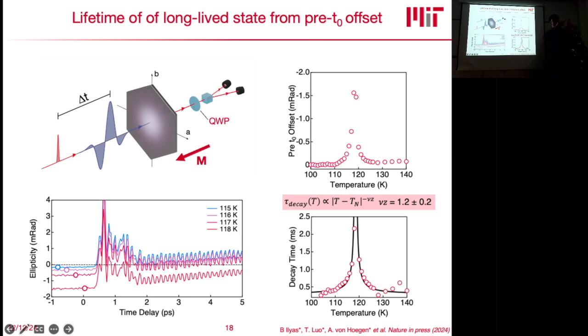But if your signal has not had time to decay back between pump on and pump off, you reference your pump on measurement to something that is still photoexcited. And if that has a positive offset, you're referencing it to something that is larger than it should be. This gives you this negative pre-time zero signal. It is not intuitive, but it is due to an artifact in the measurements, that you get this cross between positive and negative.